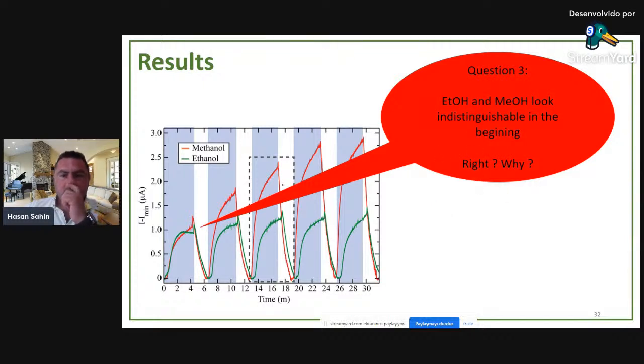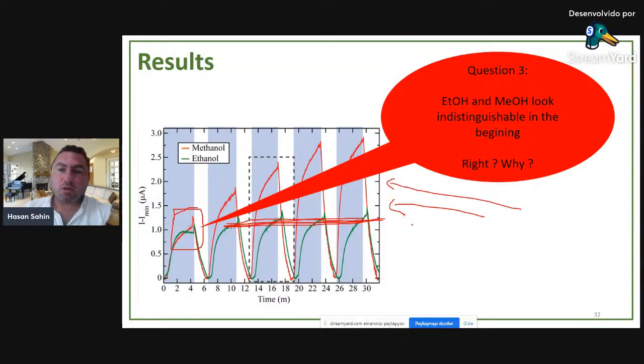And the third question is, in the beginning, as you see here, the responses of ethanol and methanol look the same. They look indistinguishable in the beginning. But in time, as you see, methanol is quite larger. The increase because of the methanol is quite larger, but the increase because of the ethanol becomes almost saturated like this. There is a saturation in ethanol, but there is no saturation for methanol. So far, I have been telling you that they are quite similar, but if I increase the concentration of VOC, they are different. I can distinguish them if I increase the concentration. It seems that methanol will be increasing much more than ethanol.